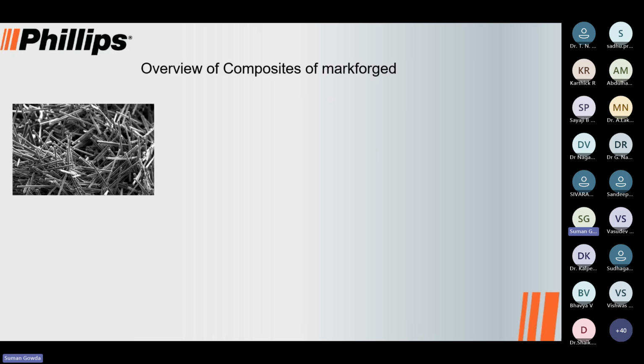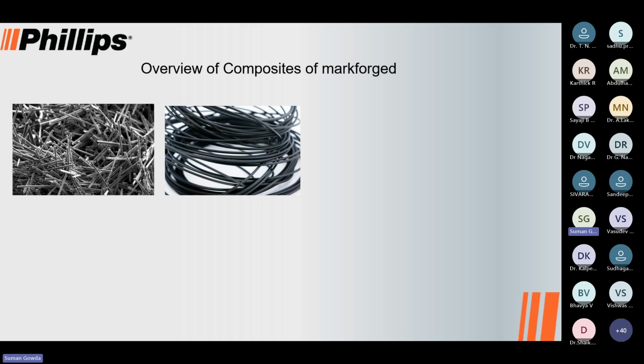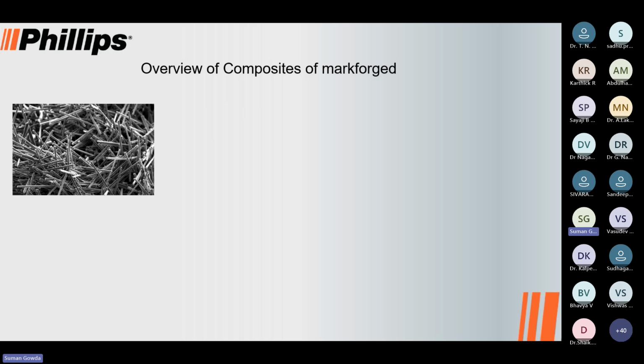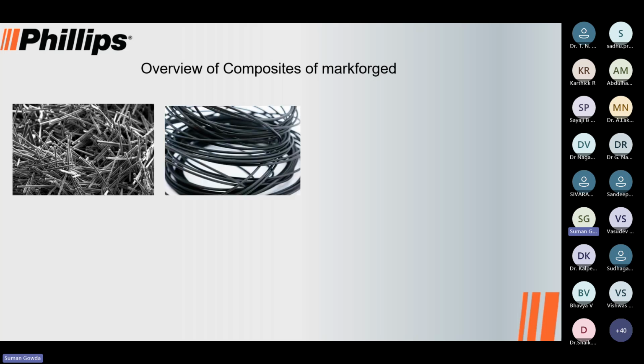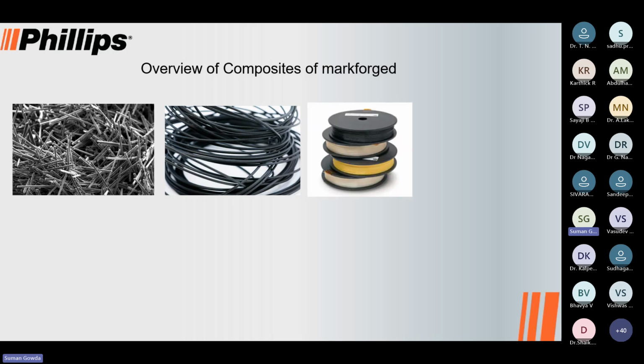And when we talk about continuous composites or fibers, there's a huge difference when we add a small amount of fibers, mix it along with our plastic components, and draw a wire. So this is what you get. The first image is a chopped carbon fiber. When we get our regular Onyx plastic wire, that is a combination of nylon plus this amount of chopped fibers. This will give me strength which is only 2 times that of a plastic. But the main strength comes when I utilize the continuous fibers.